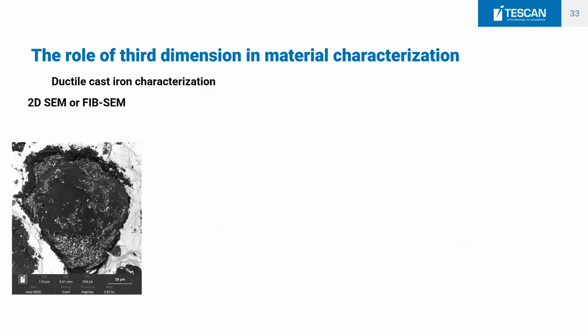So we have materials which we can observe from the surface. On the left-hand image, you can see the cast iron. This is the nodular graphite in the cast iron, how it looks. And you could see, well, it's pretty clear that it's a fractured surface and that the ductile cast iron is not featuring anything too relevant when it comes to porosity or such. You could just describe the fracture.